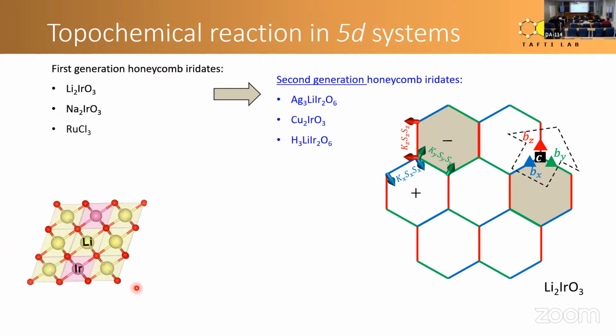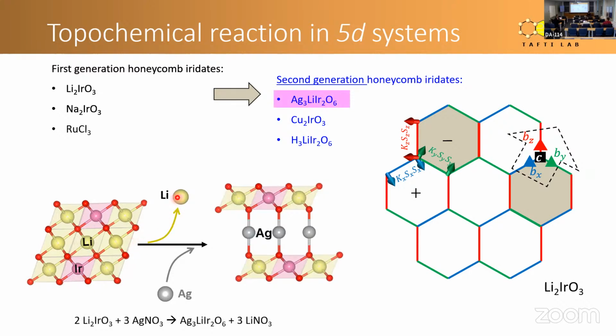For example, let's look at the crystal structure of lithium iridate at the bottom. You have honeycomb layers of lithium and iridium that are separated by layers that only contain lithium. And so here at the bottom, you have another honeycomb layer. What we do in such reactions is to take out the lithium atoms and replace them with silver atoms. Now, the top and bottom layers are still honeycomb layers of lithium and iridium, but the middle spacer layer is silver instead of lithium. Of course, that gives us a new material, in this case, silver lithium iridate.